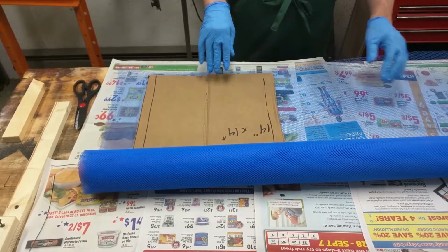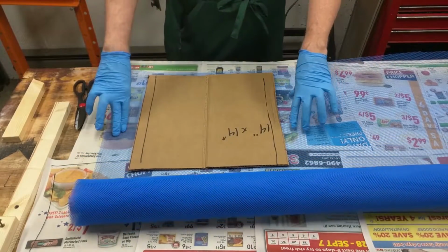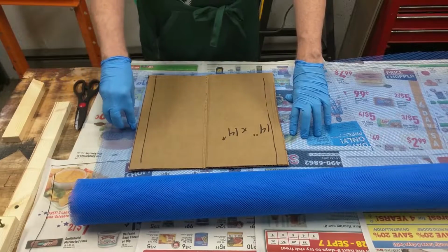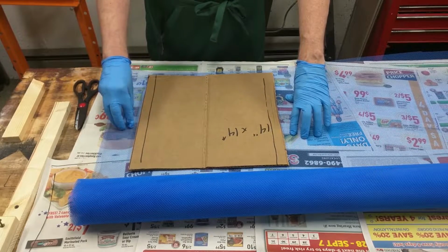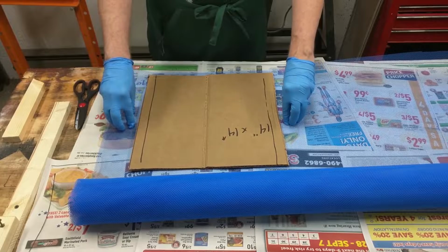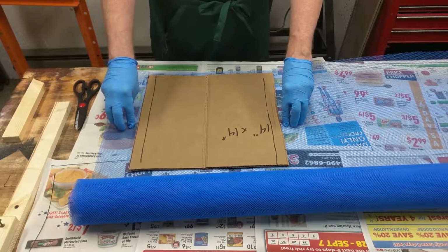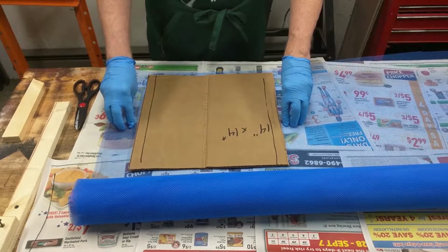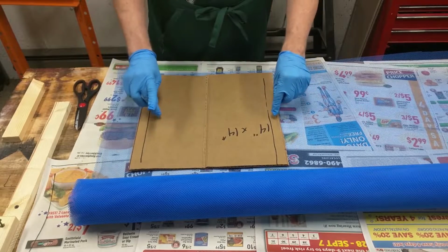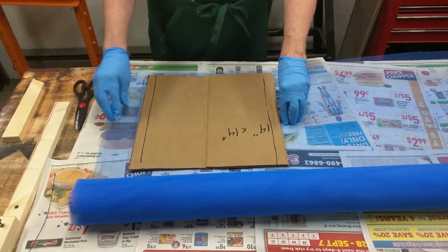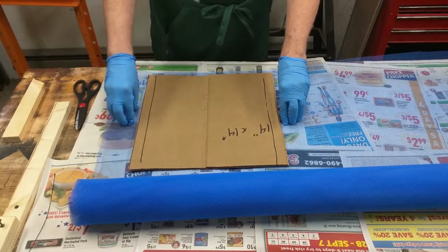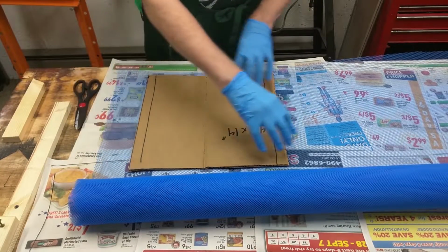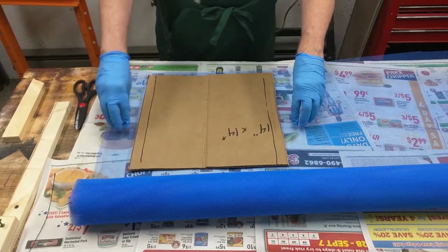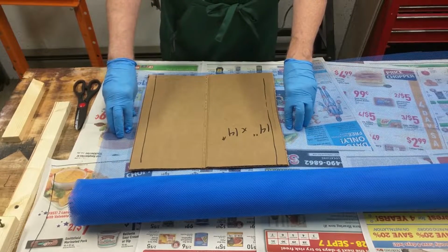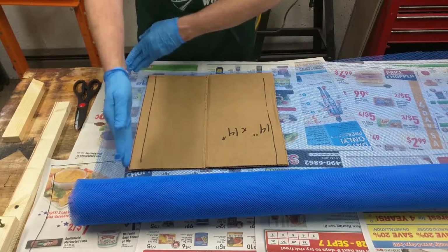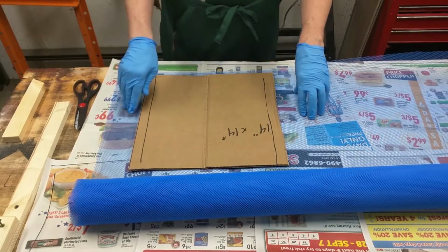I'm going to cut this piece about the same width as our part, but a little bit longer. There's going to be a port that we put where resin comes into the part and a port where we want resin to come out of the part. Now typically when we were using a mold, we would actually run our piece of carbon fiber out a little bit further, and the resin would come in and spread out and come down and then come back in again. I'm not going to use that much carbon fiber. What I'll do is I'll just use more mesh to help feed it out and then back in.